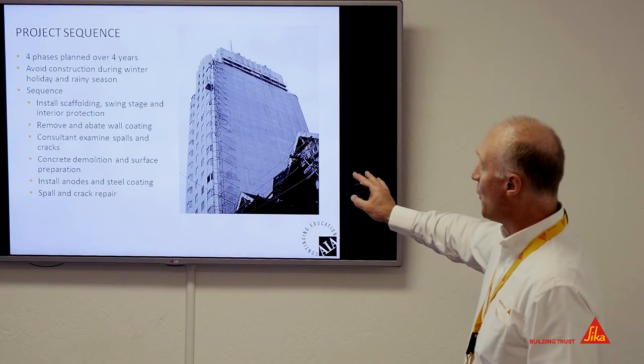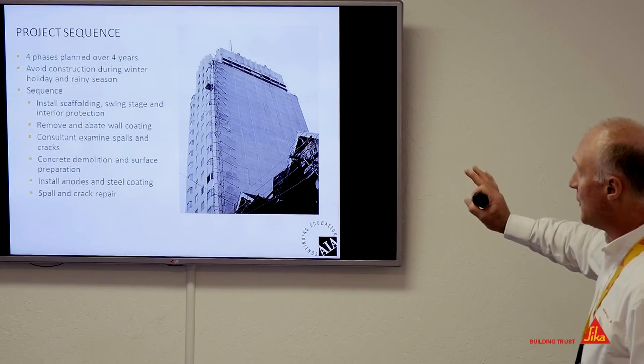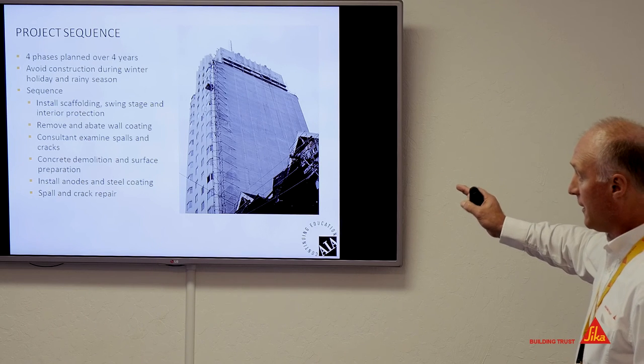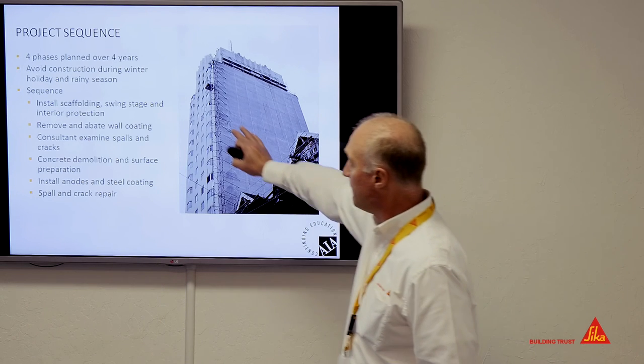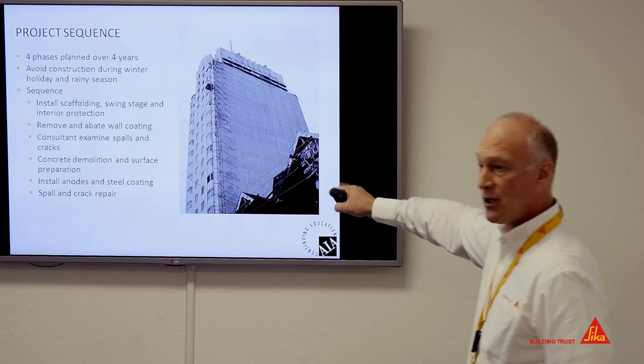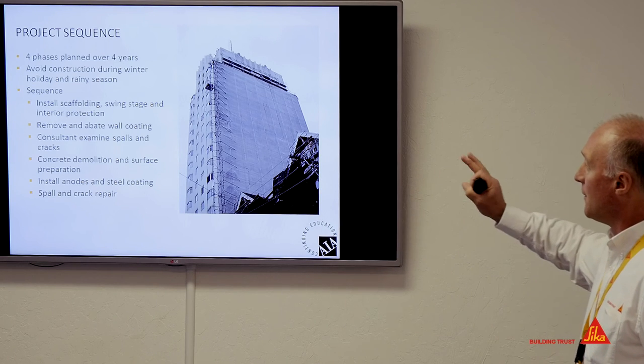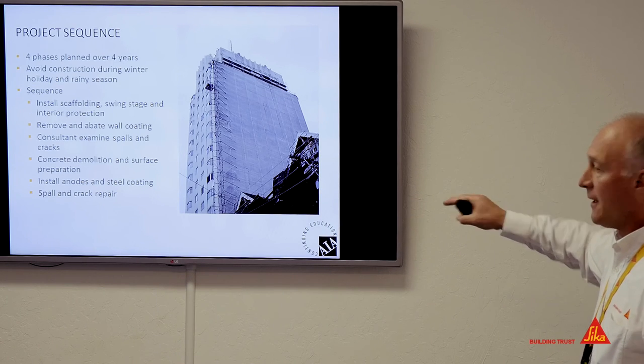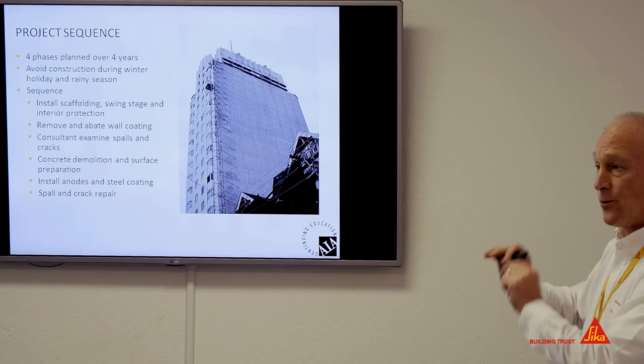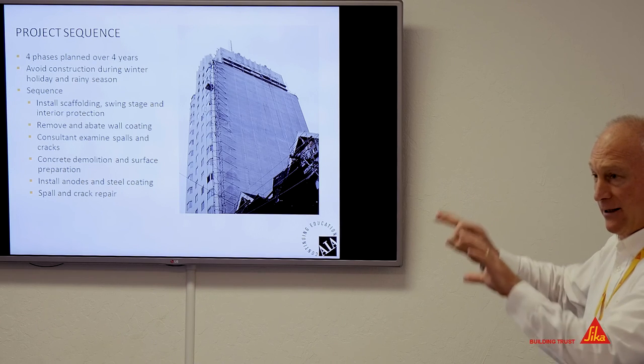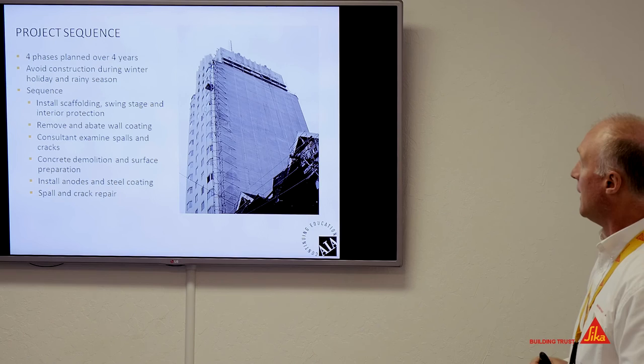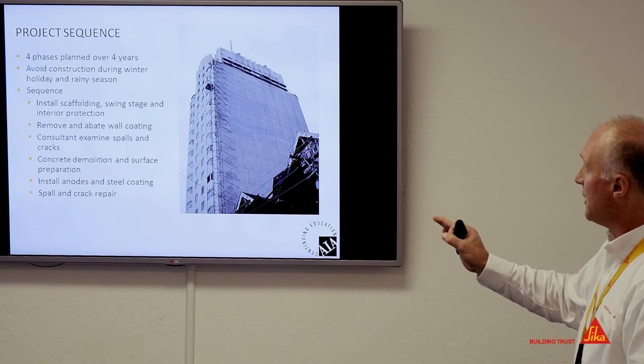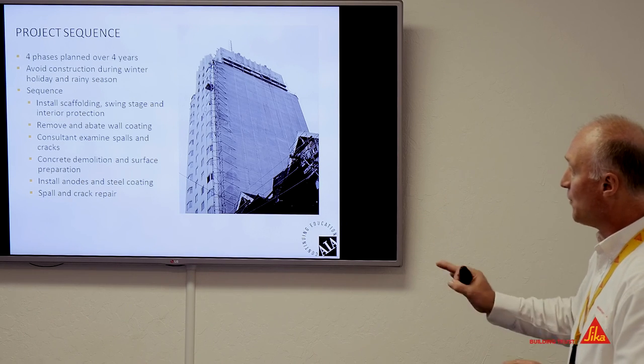They did the job in four years, four phases. They had to avoid doing any work during the winter. And the sequence was basically install the scaffolding, swing stage, interior protection, remove and abate the wall coating. After the wall coating was done, then the consultant went back up and actually reinvestigated and did all the sounding again. Concrete demolition, installation of the anodes, spall and crack repair.